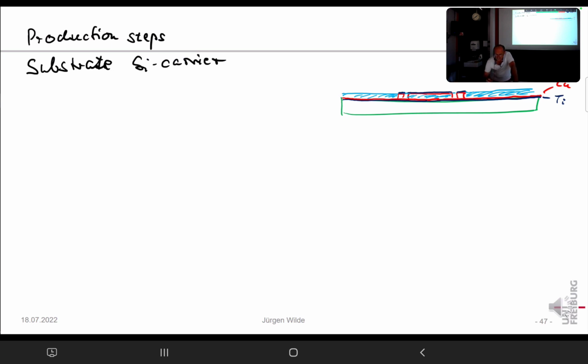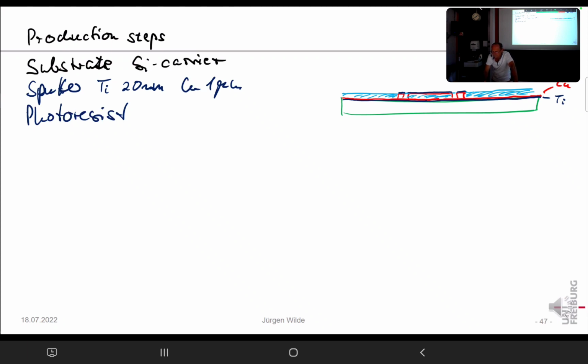Okay, so let's start. We have the silicon carrier, sputter, let's say titanium, 20 nanometer or so, just so it sticks better. Copper 1 micrometer. Then we put on a photoresist. That resist is, for instance, spun on, then expose, develop. So we have openings in the resist, here. And then we can electroplate copper.